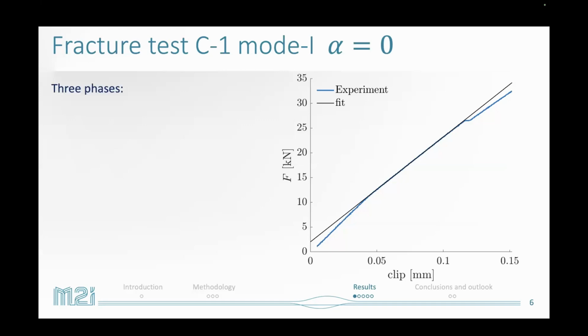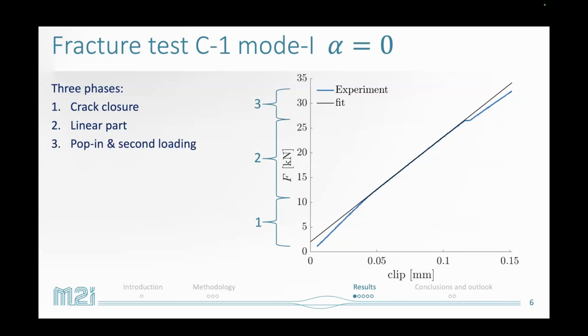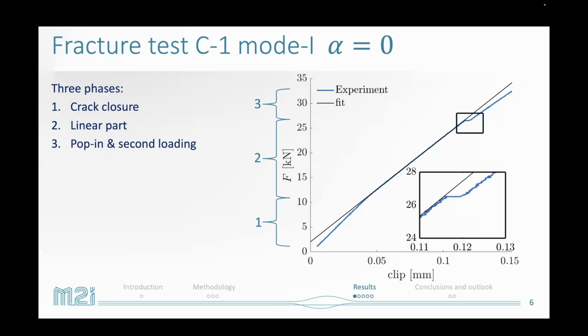And then you can distinguish more or less 3 phases. We have this first phase, in which you can see that the load comes over the crack opening load. That's where this change in slope comes from. Then we have this second linear phase in which the load increases linearly with the crack opening displacement. And then suddenly we have the third phase, which is governed by this pop-in behavior. That's a small unstable crack growth, after which it arrests again, and then by continuing to increase the load, it will finally lead to final fracture.